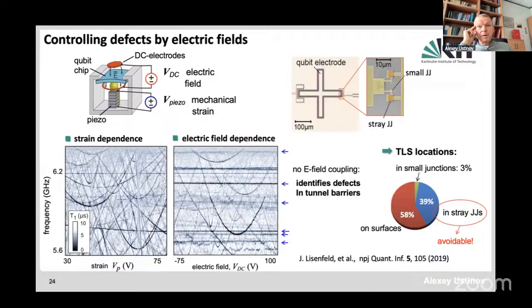And this actually reveals the possibility to fix this circuit by avoiding the so-called stray junction. Imagine that you have a thin film structure, and you go from the bottom layer to the top layer by forming a Josephson junction. In order to go back to the bottom layer, you need to make another contact between the top electrode and the bottom electrode. And this contact would require another Josephson junction in the same process, which typically is made of very large area. And usually you make this very large Josephson junction and forget about its existence. We call it a stray junction.